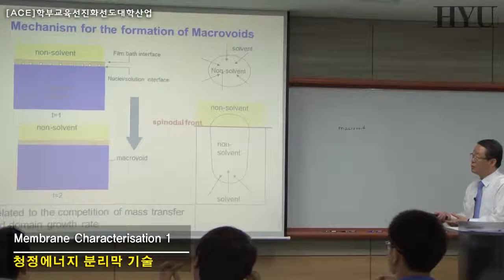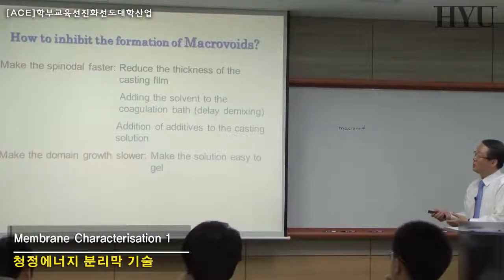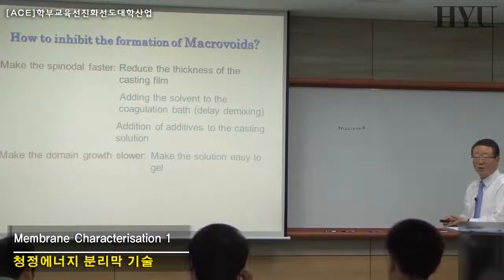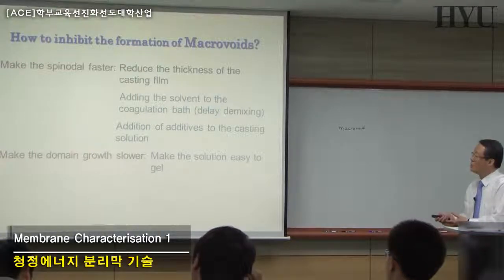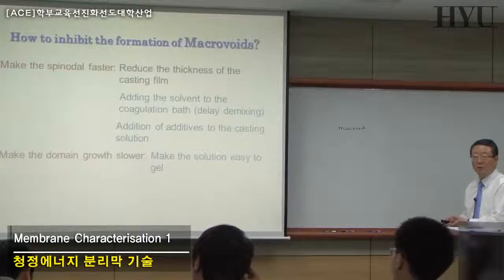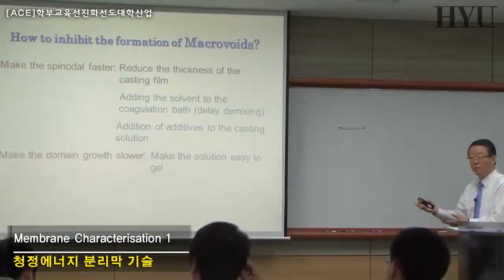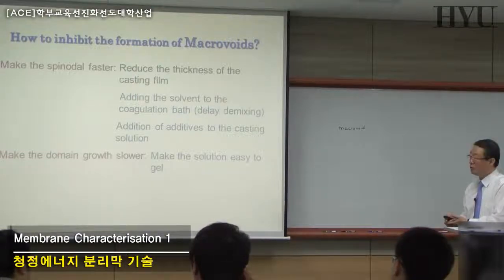That way you can reduce the time to grow, or by adding solvent in the coagulation bath, or by adding additives into the casting solution. That way you can remove your macro void and form the nicely packed sponge-like structures.